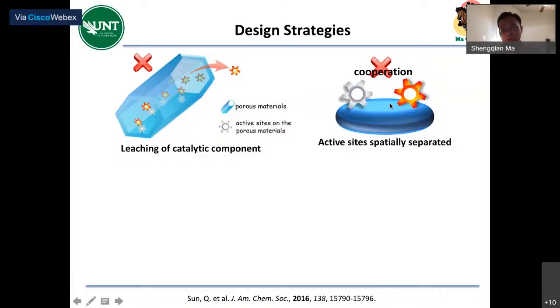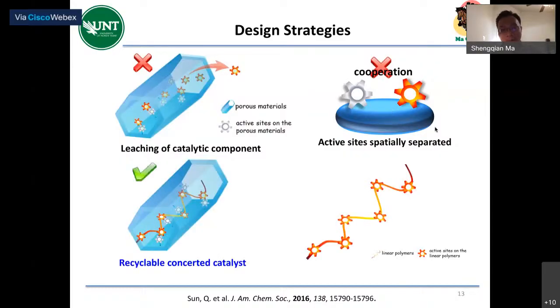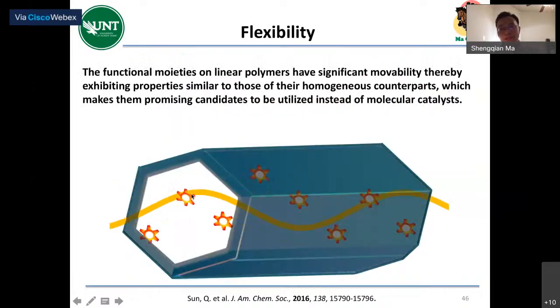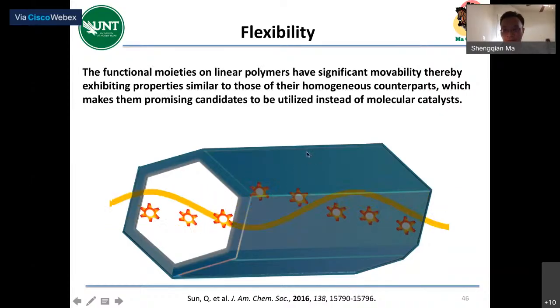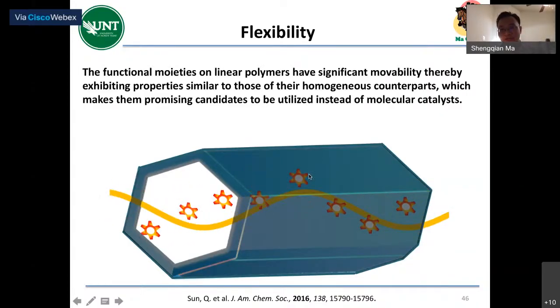This is very beautiful chemistry. It's exceptional art. And if you can achieve it, you can definitely get a very high profile publication, most of them in Nature, Science, right? But for surface catalysis, it's not easy to do precise control. So can we learn from nature, right? Nature can do this with enzyme. How about we thread some linear polymer like polypeptide enzyme, right? And put some active sites on the linear polymer and thread it in the channel or the pore of the MOF. Then electrostatically they can move, right? Cooperate. They can fold and unfold, and they can have this dynamic, like homogeneous catalyst. They can cooperate with active sites on the pore wall. And this way we can achieve the cooperativity, exactly like the enzyme. We need some flexibility, right?